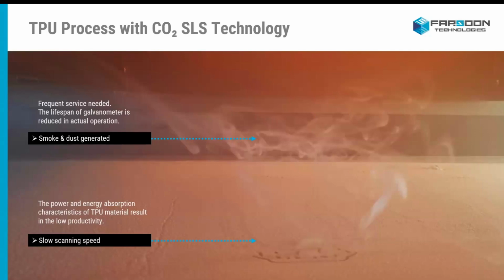So if you start at 40 watts, after 3 or 4 hours of the sintering process with all that smoke and particulate sticking to the laser window, you might actually be only getting 20 or 15 watts at the part bed. So this requires either shorter builds to avoid the smoke buildup on the laser window, or manually going in and editing the laser wattage parameters through the build process. Another obstacle is the way that the material absorbs the laser energy, which results in slow sintering speeds and low productivity.